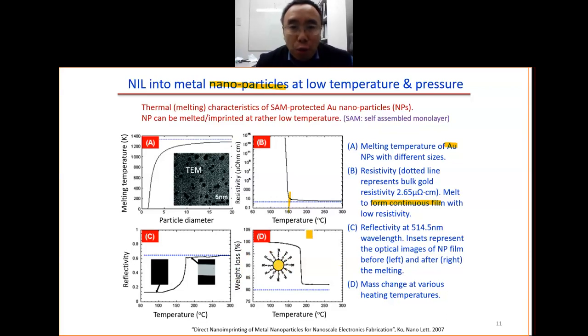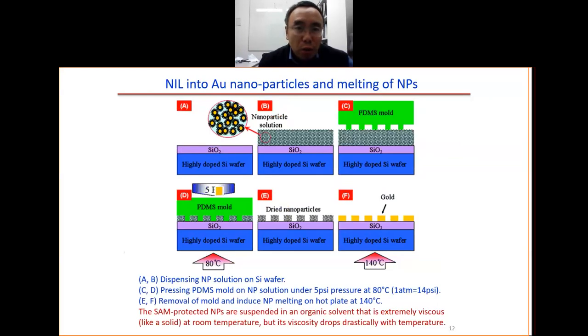But we cannot do imprint. In principle, we cannot do imprint at 150 degrees, because if we do, the particles get merged together. Once they get merged together to form the film, the melting point goes up right away, so it no longer melts. So what can we do? We dissolve the nanoparticles into a solvent. In this example, the organic solvent is very special. It is very, very viscous at room temperature, but it becomes flowable at 80 degrees.